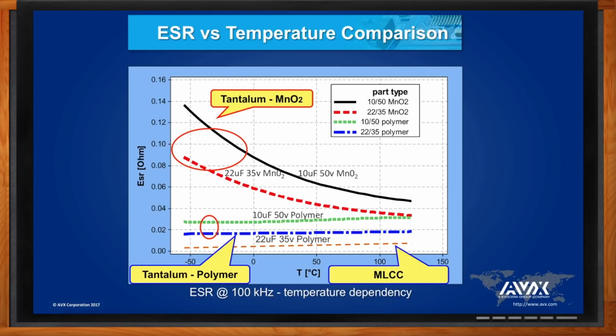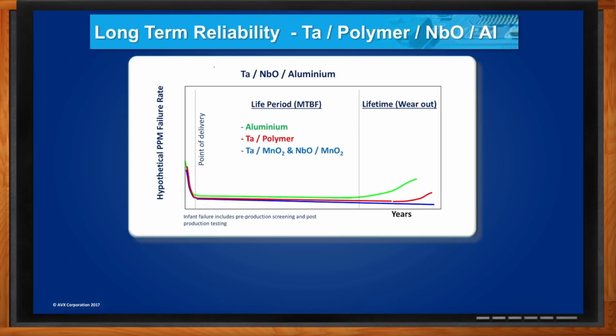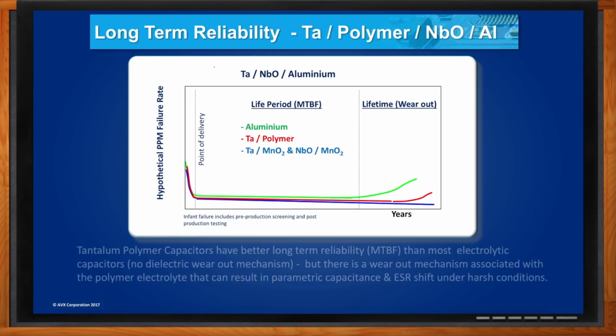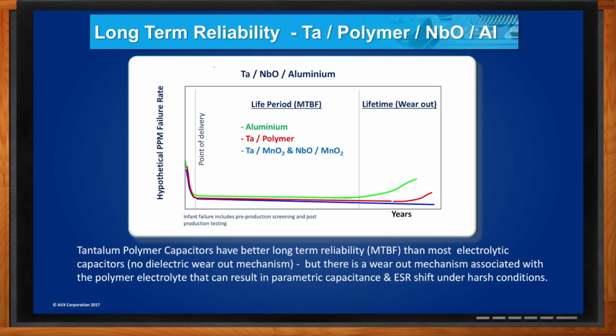So how do these technologies stack up for long-term reliability? This is interesting because if we look mainly at the tantalum and niobium family, and the MLCC, they have no wear-out mechanism inherent in the core materials of the dielectric. So in terms of lifetime, with tantalums, we have to be careful sometimes with early life failures, which we do try and contain by the voltage aging and the preconditioning we do, so that when we release them, they'll have a characteristic of very, very low ppm failure rate. And with ceramics, they just continue to improve over time. The longer a tantalum lasts, the more likely it is to last longer because there's no inherent wear-out mechanism there.